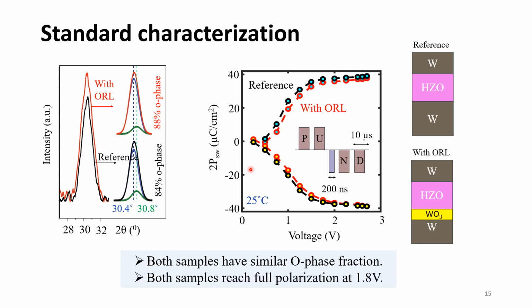And this could be clear from the electrical measurement shown on the right. So the black curve is coming from the reference device and the red one is coming from the ORL device. So we have applied different voltages and used 200 nanosecond pulses to switch the polarization. As you can see here, both the devices have very similar saturated polarization and also very similar coercive voltage. And I would like to mention here that both the devices show 100% switching at 1.8 volts.